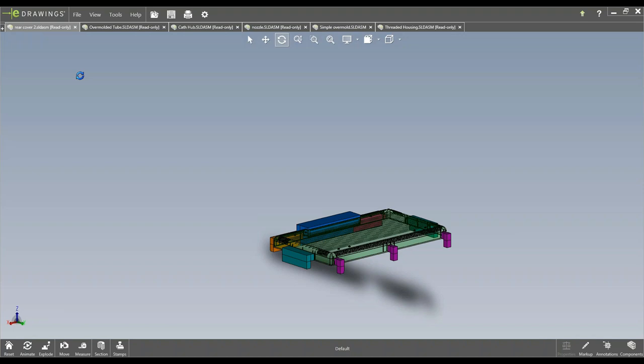Not to say we can't get there because we're doing things quickly. So what our process is, we'll take your CAD and add the recommended shrink rate per the material that was chosen, apply that to the mold design. And that's what we cut our tools to, and we cut our tools to a tolerance of plus or minus five thousandths of an inch, usually tighter than that. But in a well-designed part that will translate to the plastic.